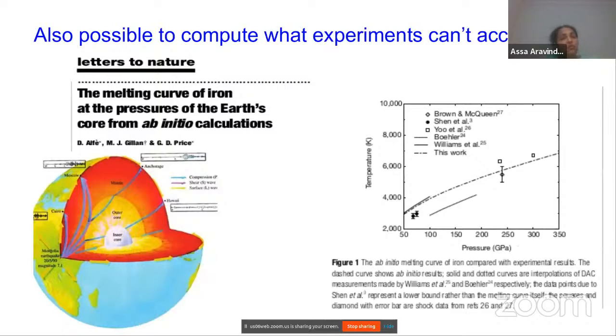So far I was telling about what DFT can do and what experiment is doing. Now it is also possible to do things which experiments cannot do. For example, the melting curve of iron. If you want to do such a thing, you cannot just go inside the inner core of Earth and do the experimental study. If you have to reproduce it, you have to maybe recreate the extreme conditions of pressure and temperature, maybe using an atom bomb explosion or something like that. I was just vaguely saying, but yes, these are things experiments cannot do very easily, but using DFT or ab initio modeling, we can in fact reproduce these curves, which can exactly reproduce the pressures, and which can be equated to the temperatures in such extreme situations. So these are some examples in which experiments are difficult to perform, but DFT can at least give a qualitative idea of what physical phenomena can be happening there.